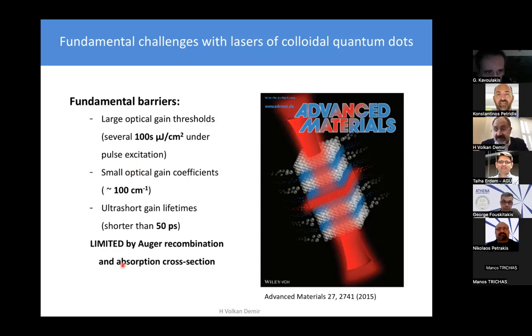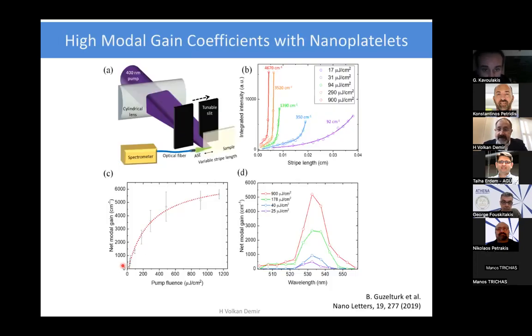In our case, our strategy was to go to colloidal quantum wells because we can make them laterally larger. We can actually have larger volume while keeping the confinement tight in the vertical direction. Another approach, as several other groups look into, making what is called giant quantum dots. Giant quantum dots, of course, there's still a trade-off, but Auger you can reduce significantly. In our case, we had been looking into pushing the gain performance of these quasi-two-dimensional structures, and over the years, obtaining higher quality crystals and indeed going for higher pump.